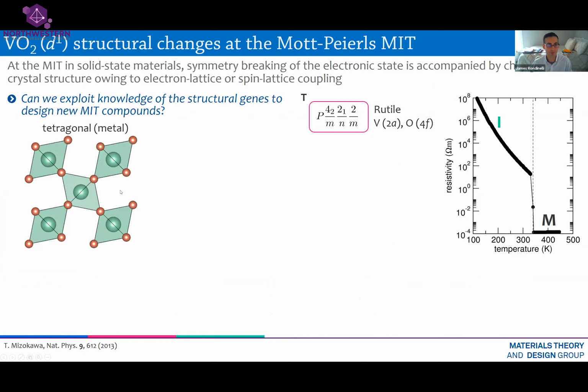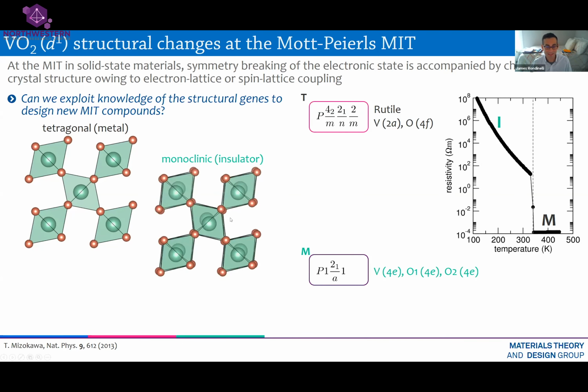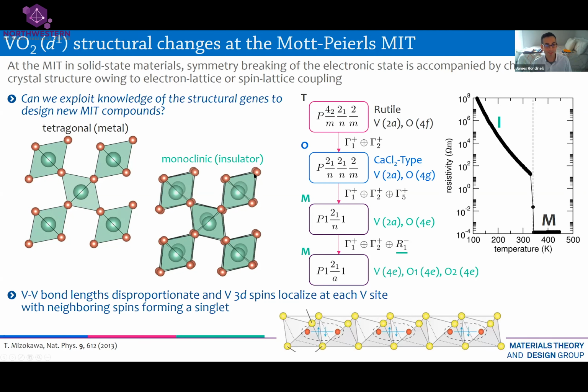And the structure now is shown in a slightly different perspective. So instead of looking transverse to the chain, so you see those one-dimensional chains of octahedra, I'm looking down them. And so the chains are running into the plane of the screen that you're looking at. And this is the transition. In one phase, the material's insulating, again, at low temperature, and at high temperature, it's metallic. There's a lot of details on the slide. The details don't really matter, but what happens across this thermal transition is that the insulating phase has a change in the structure. Grossly, it's the same, except for the fact that the vanadium atoms start to get closer and closer together. And in the tetragonal phase, the high temperature phase, this black one, the structure is metallic, and all of the vanadium atoms are equal distance from each other.